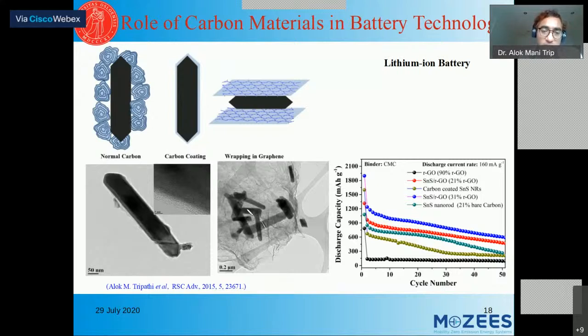So what is happening with this one? Basically, why are we using the carbon? One is that it stores the lithium. Second is that it works as an electron conducting medium inside the electrode. If some reaction occurs between lithium and tin, the electron removed goes through this carbon material to the current collector, and then finally out of the terminals. Here is the charge and discharge capacity of this cell, comparing all three kinds of carbon.